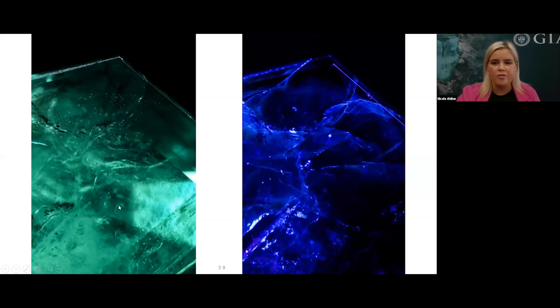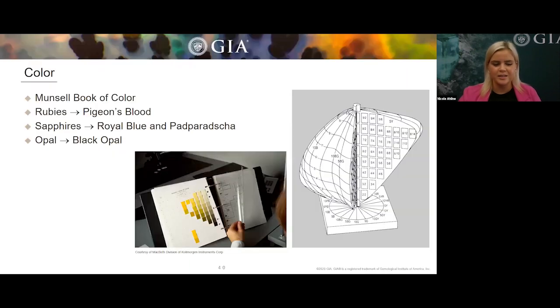But then when we turn off that dark field and we only use long wave fluorescence, these filled fissures just light up, and it's super helpful for us to find those low relief fissures and help us get a guide on what our call is going to be if it's an F1, F2, F3. Again, that's minor, moderate, or significant residue in these stones. And kind of just like that lavender jadeite with that orange dye, again, not all filler for emeralds will fluoresce to a long wave. This is just a very perfect example to show you all.